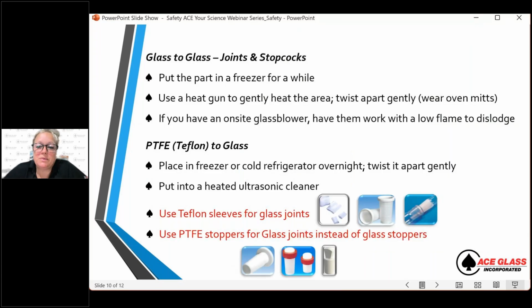A lot of issues that we also find is that people get stuck joints and stopcocks. So a lot of times you have a standard taper joint and you put some grease on it to make it seal very well, and then you put your stopcock on there or another joint, and when your reaction is over, you just cannot get it apart. So ideally, if you have small lab glass, you would put it in the freezer. That's the easiest way to go about it. Leave it in there for a while, and then try to twist it. They should be contracted enough to where you can get them apart easily.